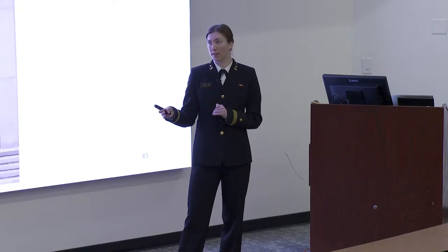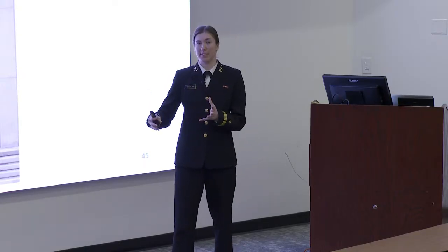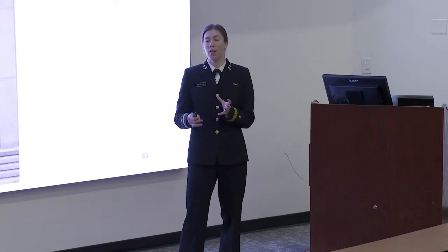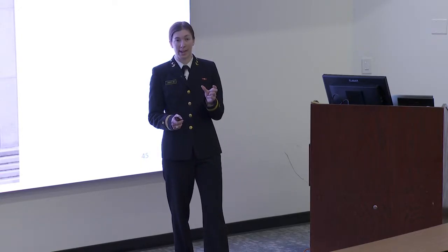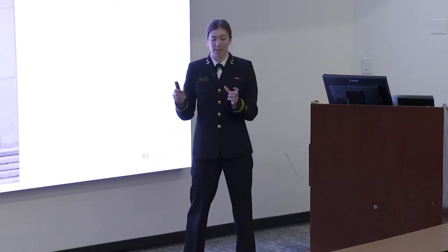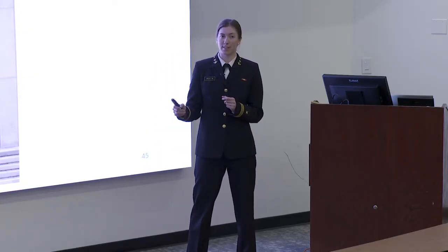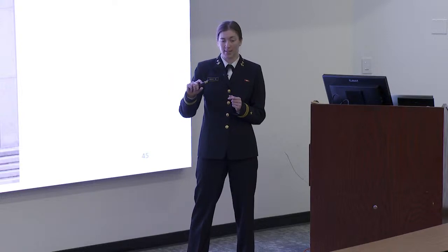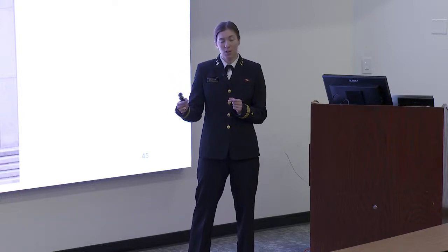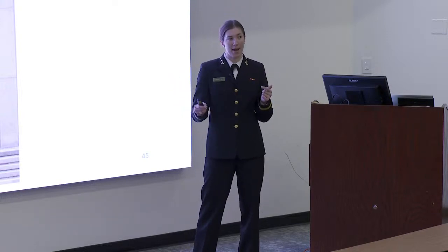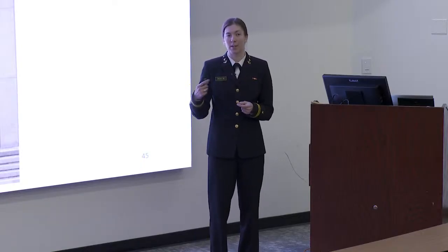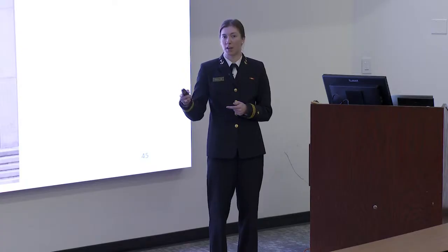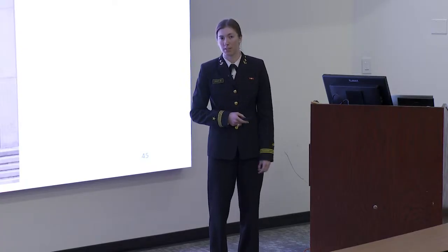I think once we have really cemented the filament process, because right now the problem is creating a filament that isn't variable in diameter, because the Filabot extruder is very sensitive, so even the slightest increase in speed of the screw or how fast it's spooled can impact the diameter. Once we create a filament that is very uniform in diameter, we can graduate to a higher quality printer.